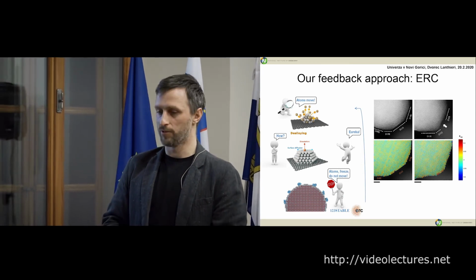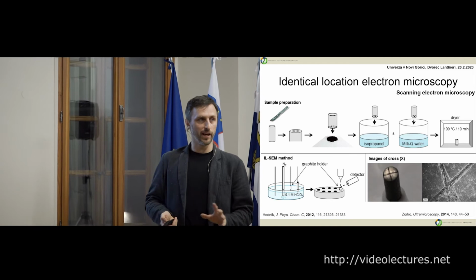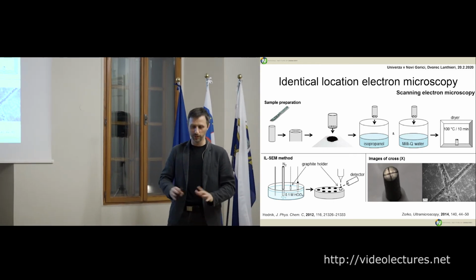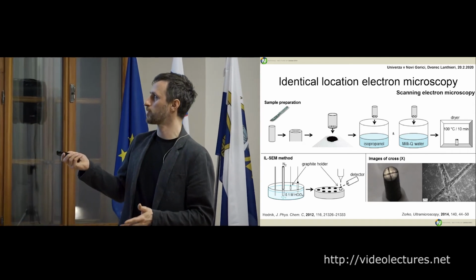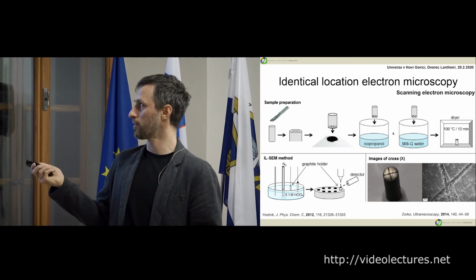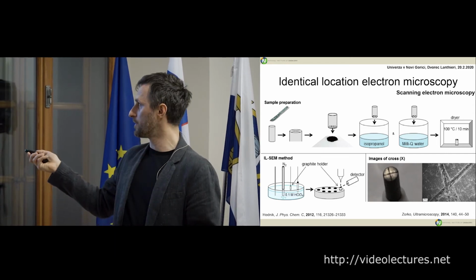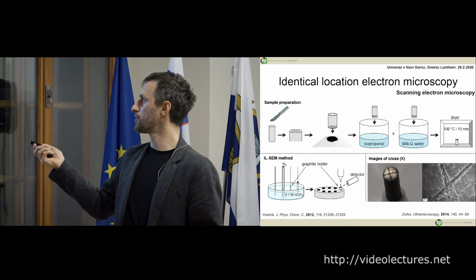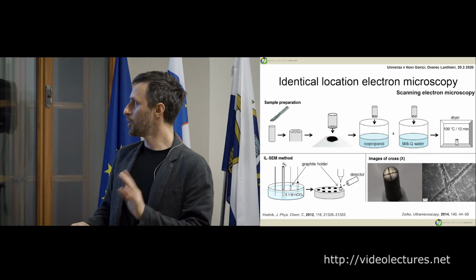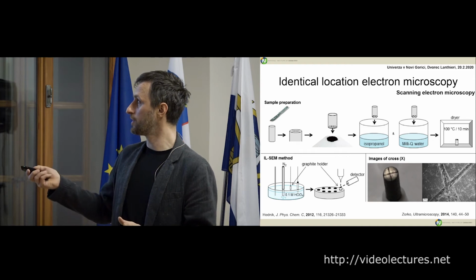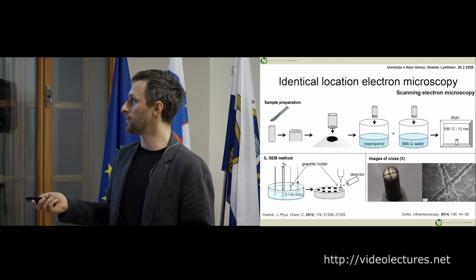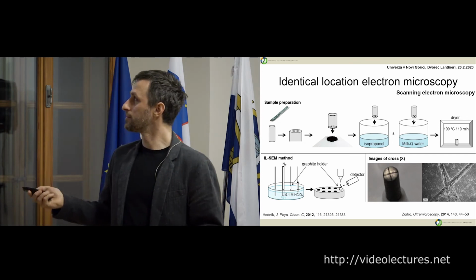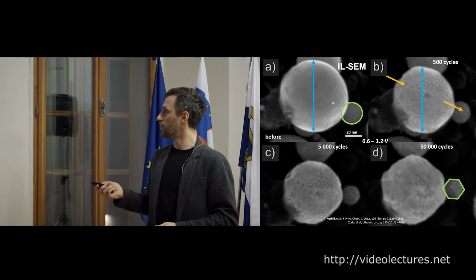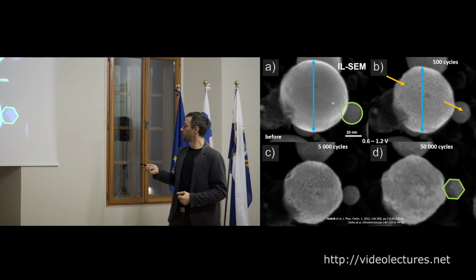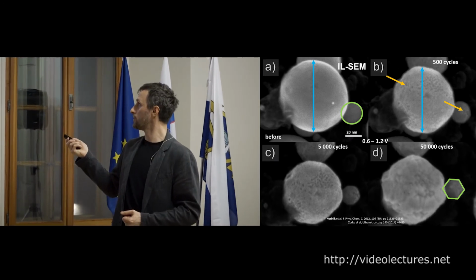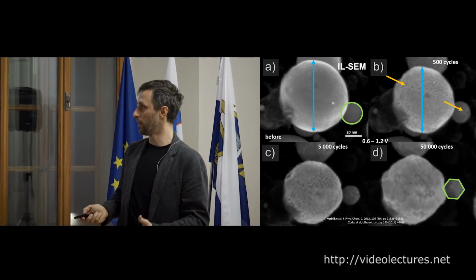Now, just for fun, you can also do this identical location with the SEM. And I think you can also do it with any microscope. So here it's super simple. You take a graphite pencil, a graphite rod, you make a cross because this will help you find the spot afterwards. And then we have this cleaning procedure for the catalyst. But you can also do EDX, of course, if you have it in the SEM. This was done in 2012 with our SEM, which is kind of good, but you already see all these effects. So you see porosity, you see shrinkage, and you see the shaping on platinum copper.